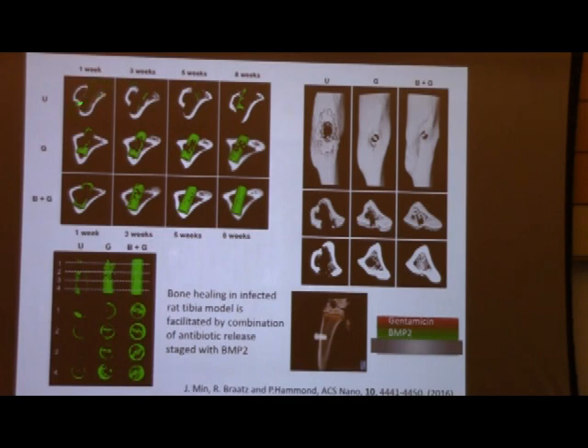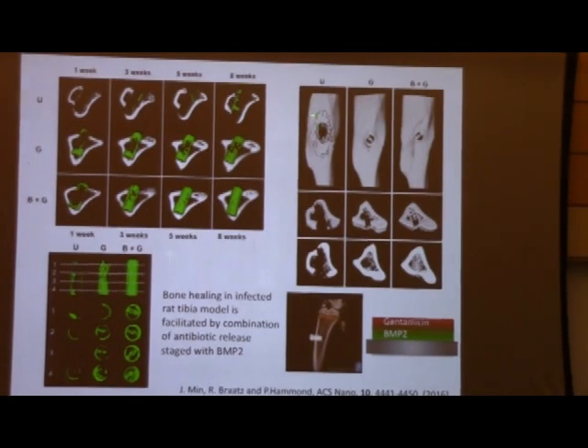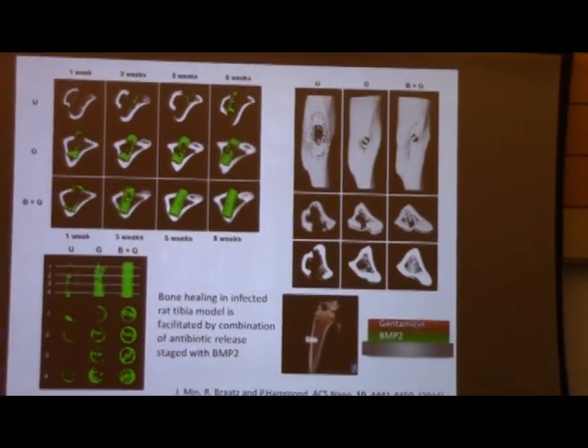In some cases, we look at untreated implants, and we look for the regeneration of bone around that implant. Instead of bone regeneration, we see that although some bone tries to get deposited over time, we're really seeing a lot of resorption of bone. Here you can look down at the micro-CT and you can see where the bone is getting kind of etched away because of the byproducts of this infection. If we just have gentamicin present, but no growth factor, we're able to fully eliminate the infection, which is a good thing. And by eliminating the infection, over a long period of time, bone is slowly trying to reestablish itself. And you can see that here with the G representing gentamicin.